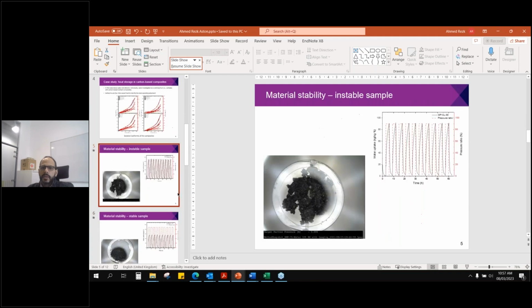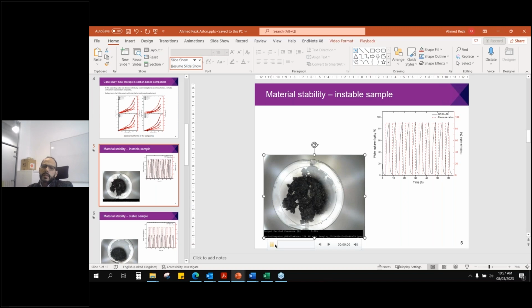The next step, actually, we need to look at the repeatability and stability of the material. So we apply extreme partial pressure on the material between 0 and 90%. Sometimes you can call it partial pressure, sometimes you can call it relative humidity if you're coming from the humidification and dehumidification industry. So we apply this extreme, and we can see that some materials are very stable at low and high concentration of water vapor and ethanol, right?